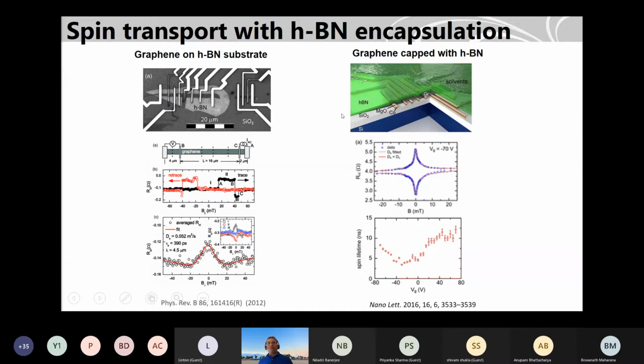And then this is with a substrate, and then people have done it with a capping, so that first they put the ferromagnetic contacts, then put the graphene, which is encapsulated with boron nitride. So they find out that the solvents and contaminations also can affect the spin lifetime properties. And here they could show spin lifetime up to 10 nanoseconds, actually, which is quite good.